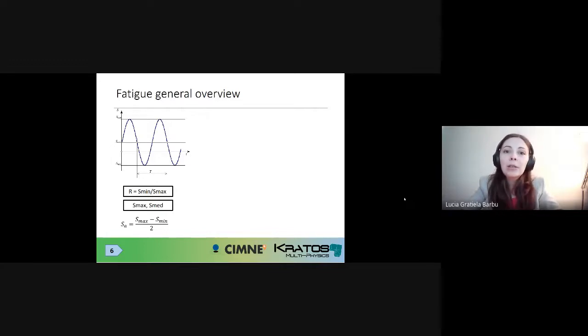Okay, so we have a cyclic stress state at each integration point, and based on this stress state we can compute a reversion factor, called the stress ratio, this R factor, which is the ratio between the minimum level of stress recorded at that integration point and the maximum level of stress recorded at the same integration point. So throughout our geometry, all of the integration points inside all of the finite elements have their own specific stress ratio, okay? Of course, we can compute the maximum level of stress inside the whole geometry, the maximum stress ratio inside our geometry, etc. But that is just to explain what this stress ratio is.